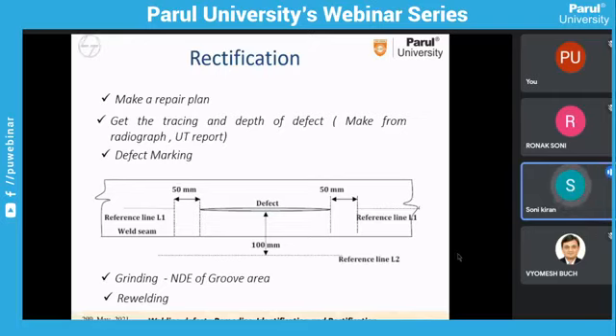And the standard procedure is like that. Here is a horizontal seam, and in the center there is a defect that we have identified. Now with radiograph or UT, once we got the tracing, tracing is nothing but like a butter paper on which we mark everything, and with that butter paper we mark the defect location on the actual job. Now before doing any grinding or any further rectification, we have to mark some reference lines to identify whether the defect is gone or not after grinding. So for that we used to mark defect reference lines like 50 mm on the toe side and sideways 100 mm. And with that reference, after grinding, we used to check whether the groove is at the proper location, and the proper depth we need to ensure.